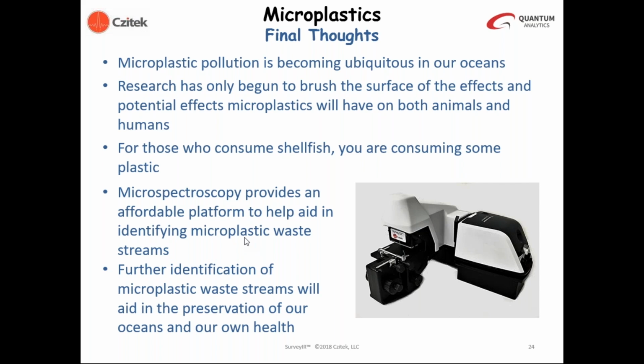If the plastic is embedded in the filter material, or it's really very thin, then you get better results by removing it from the filter paper and putting it onto what we call Low-E glass slides, which are really microscope slides. They are glass substrates, but they have an infrared reflective coating on them. We thin that out with a roller knife, which is a knife with a bearing on it, and that thins the sample out. And then we analyze it by reflection absorption in that way.